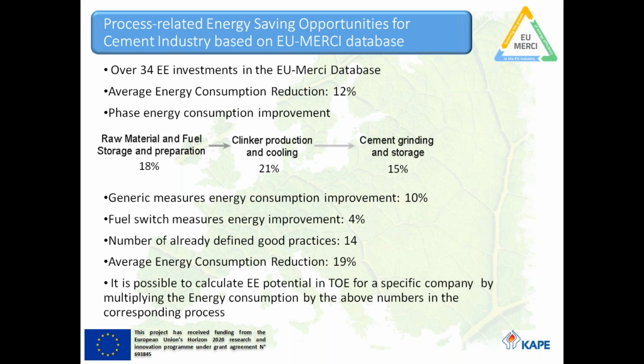And the generic measures, so not related to any of the processes mentioned above, but the non-process specific measures, on average give around 10% energy efficiency improvement. Fuel switch measures have been identified to provide on average 4% energy efficiency improvement. During the project, we have already identified 14 good practices which have an energy consumption reduction of 19%. They are, however, highly process related, so they have not been listed on the slide.